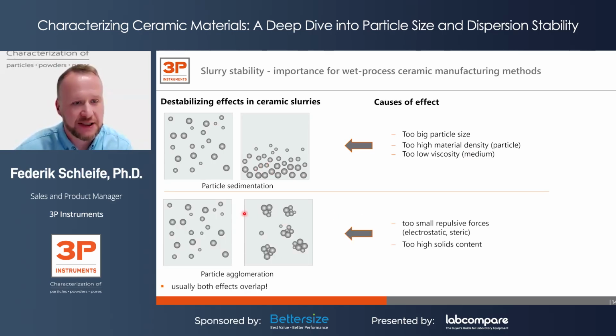And a second destabilization effect that is an issue in the manufacturing of ceramic pieces is agglomeration. If you have too small repulsive forces, electrostatic or steric, between the particles, or you have a really high solid content in your ceramic slurry, those particles might tend to agglomerate, and therefore you don't have a stable particle size. And as shown before, when the particle size changes over the process, of course you cannot secure that you will have the final properties you desire. Usually both effects overlap with each other, and I'll show you an example which makes it pretty clear that sedimentation or agglomeration would be an issue.